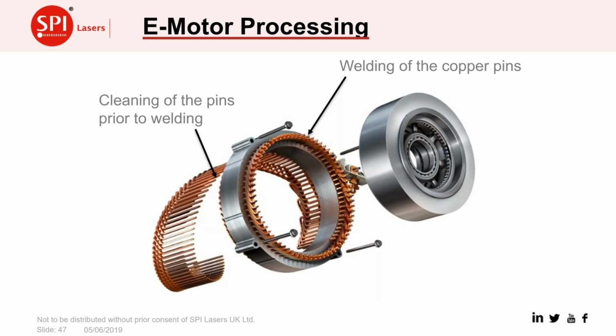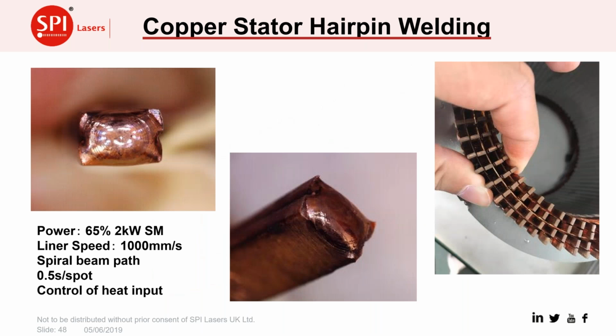Another area where laser welding is important is in the making of the electric motors. These go to very high volumes. The production processes need to change. And what they've come to is these hairpins that need welding together. Actually, another type of laser, the pulse lasers that we also make, are often used for cleaning of the insulation and generally cleaning of the hairpins before they're welded, but then we can use the laser welding for joining them together, and they're joined together in pairs after they've been fitted into the electric motor part.